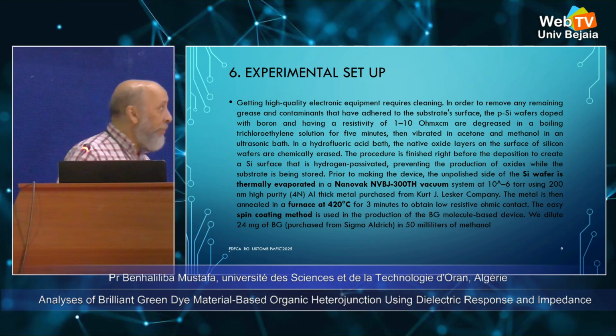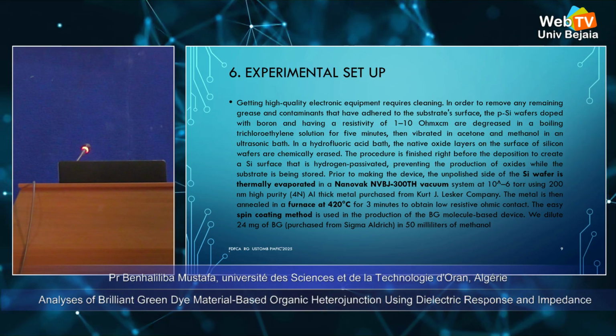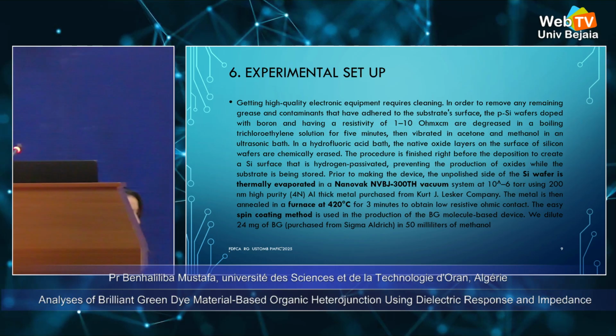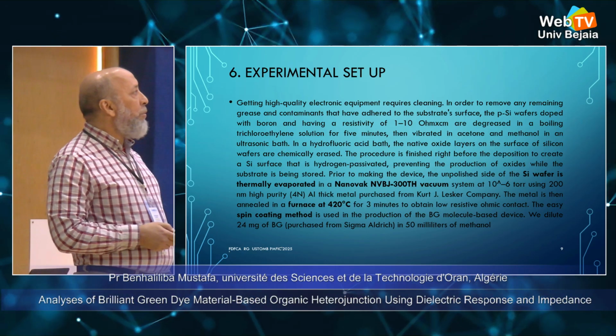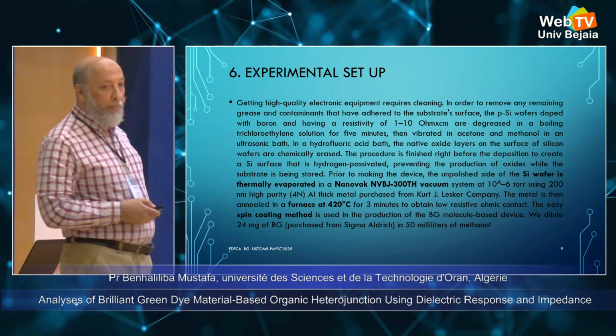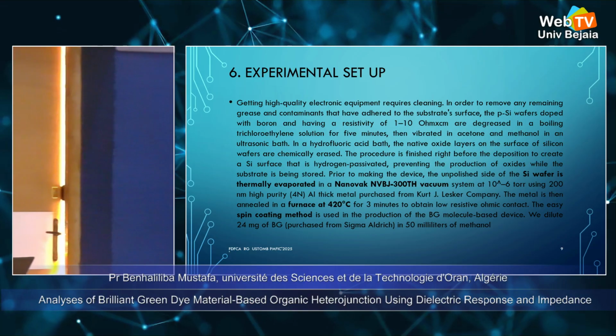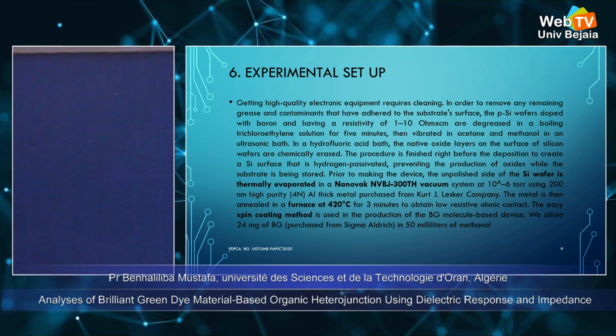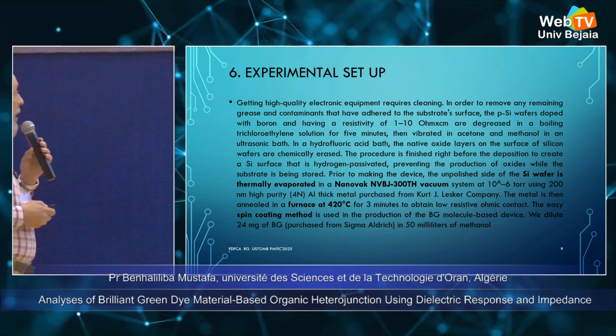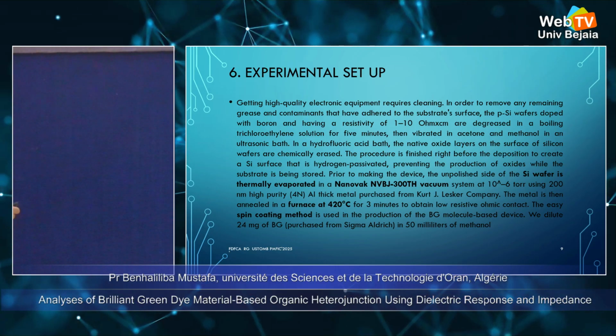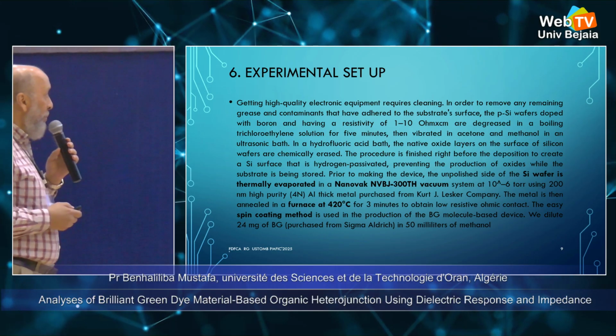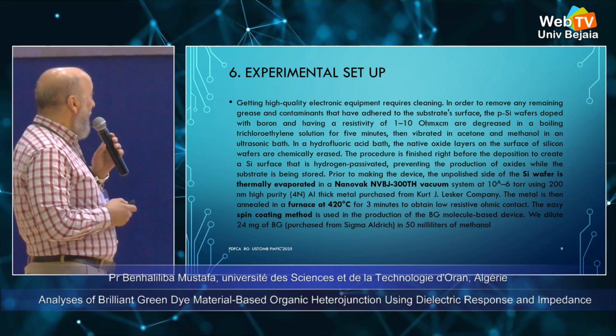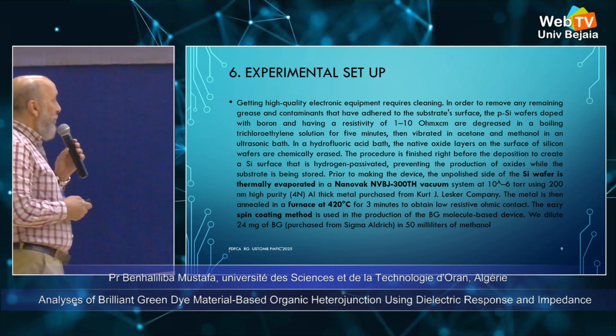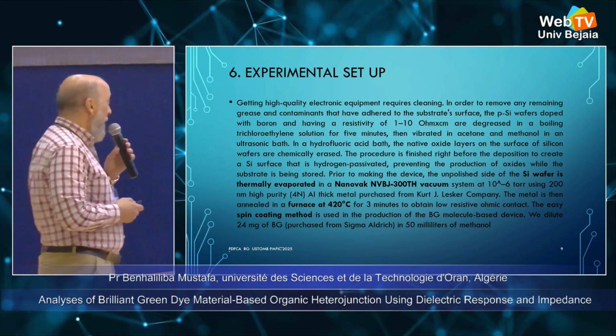Experimental setup. Highly quality electronic equipment requires cleaning in order to remove the remaining grease and contaminants that have adhered to the substrate surface. The P-type silicon wafer doped with boron and having a resistivity of 1 to 10 ohm centimeter is degreased in a boiling trichloroethylene solution for 5 minutes, then vibrated in acetone and methanol in an ultrasonic bath.